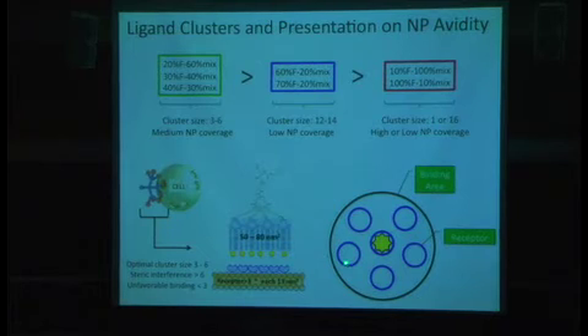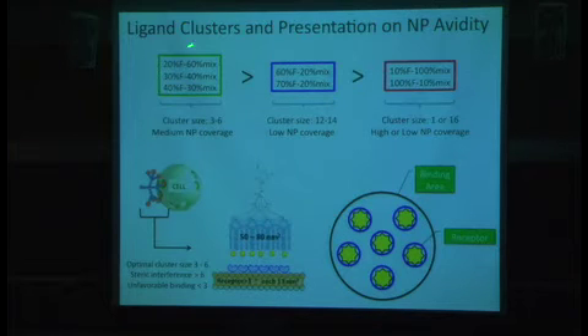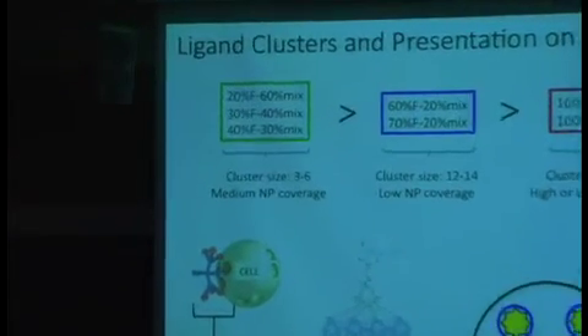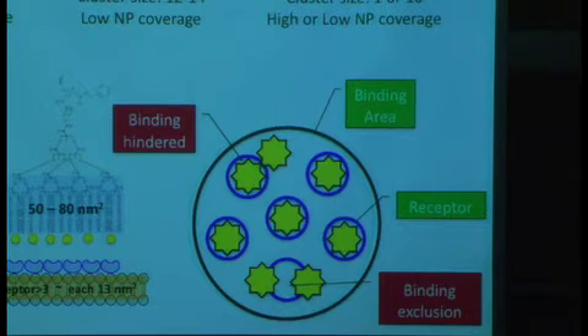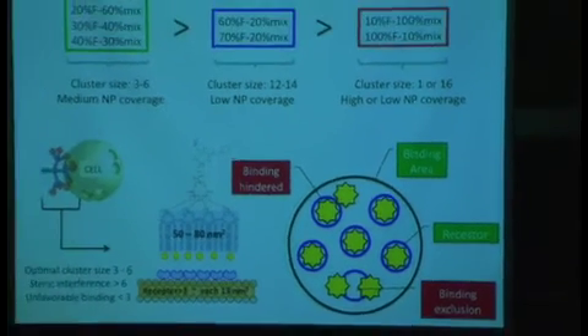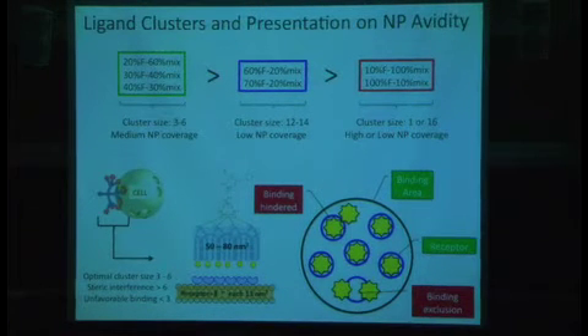When we just have singular functional groups on these dendrons, we're really not optimizing the amount of interaction that we can get, the number of active binding events that we can get in these systems. As we begin to increase, we see that the systems in this range between the 20 and the 40% folate were the highest bars. They fall in this range of 3 to 6, which gives us more optimal binding. And when we get beyond that, we begin to see steric effects, binding hindrance, and binding exclusion effects due to the larger cluster sizes. We also think that there's a tendency on the cell membrane for these folate receptors to pre-cluster. They float on lipid rafts. There's been some imaging of the cell membrane surface, and it's been reported that these tend to cluster in groupings of about 3 to 4. If that's true, that may explain why our 20% or our 3-cluster group actually gives us the best performance out of all of these, as opposed to the higher cluster size that fits within this range.